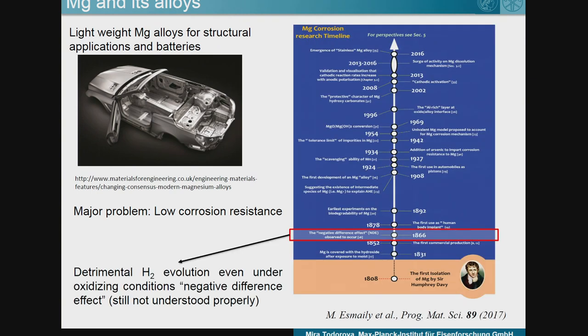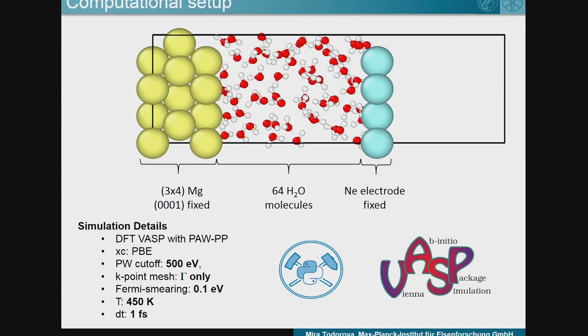It also exhibits a very strange corrosion behavior. Now, at anodic condition, which means that magnesium is positively polarized, there is observed, apart from a very high corrosion rate, also the evolution of hydrogen, which is completely counterintuitive and has puzzled people for more than 160 years. So we thought, okay, now we can maybe perform a calculation at anodic condition, look at what's happening, and we can really look at the electronic structure, at the atomic structure, maybe we can understand what's going on.